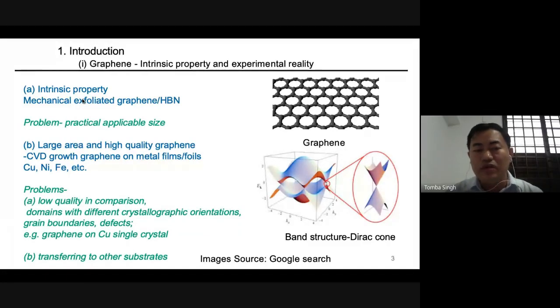For large area growth, we can use CVD, chemical vapor deposition growth, on metal foils or metal films, metals like copper, nickel, iron, etc. But what is the problem here? The graphenes on these metals are of low quality, and there are many domains of different crystallographic orientations, and grain boundaries and defects are there. For example, if we pick graphene on a copper substrate, there are lots of domain orientations because of the weak interaction between the copper substrate and the graphene.